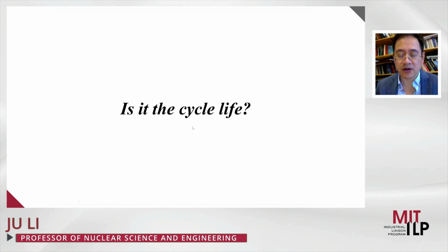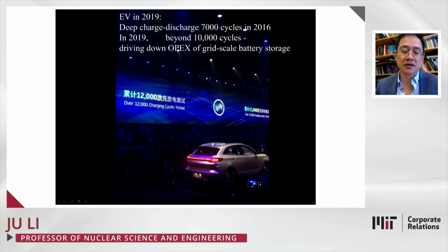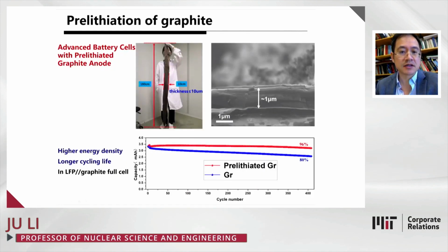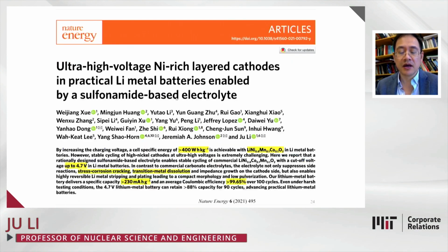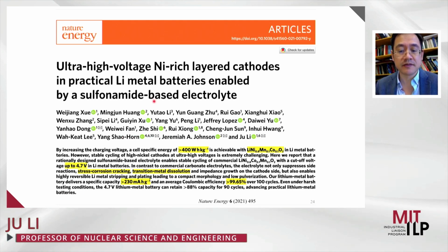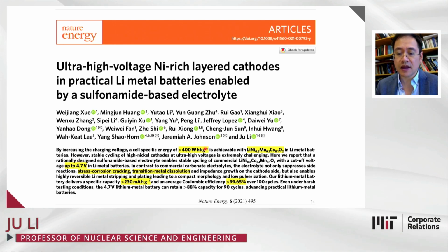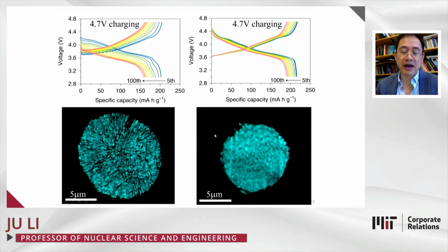So there were questions about battery cycle life. However, after recent years of study, for example, by Professor Jeff Dahn's group, this really is not the bottleneck. So by developing technologies such as pre-lithiation, where we load up the graphite with some initial lithium inventory, or by improvement of the electrolyte formulation. For example, we have done some work with Professor Yang Shao-Horn and Professor Jeremiah Johnson, where it was shown that by using this new solvent, a new family of electrolytes, we can achieve both very high voltage charging of the nickel manganese cobalt 811 cathode, as well as with lithium metal or graphite electrode.